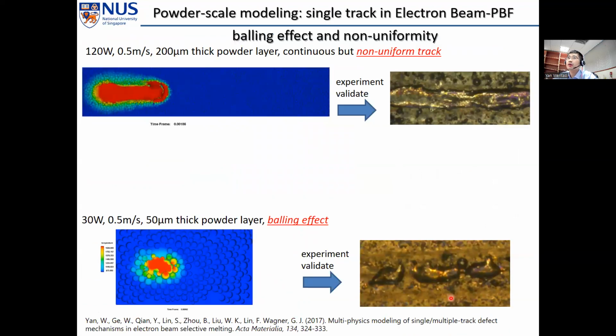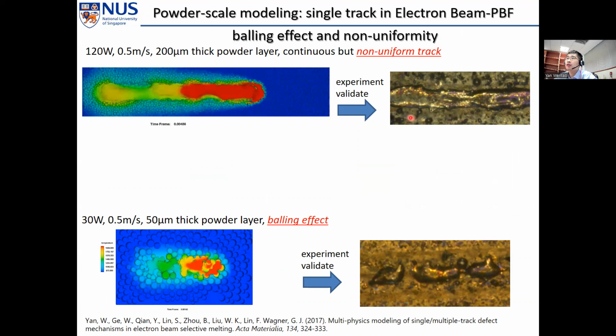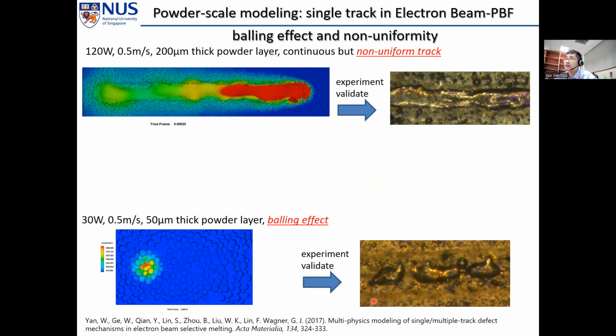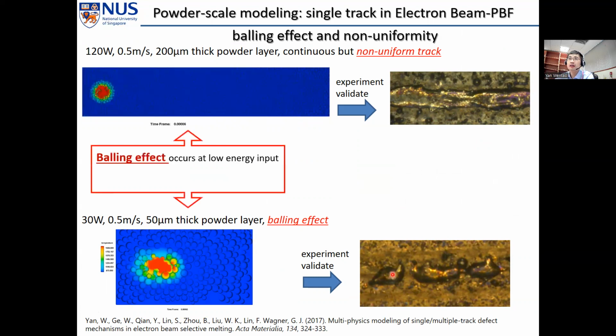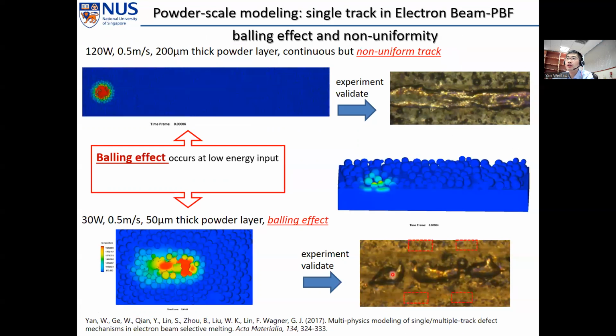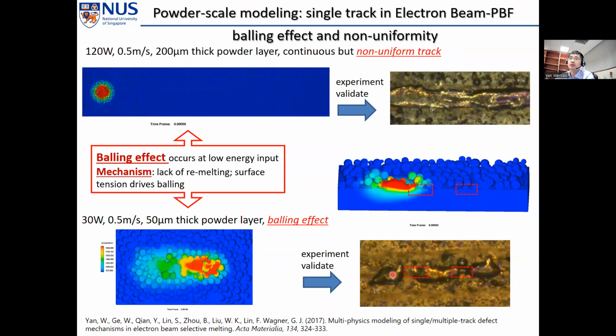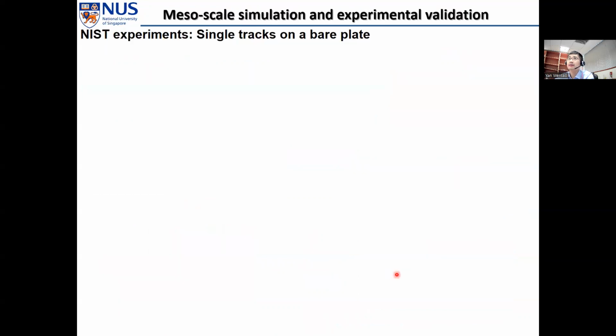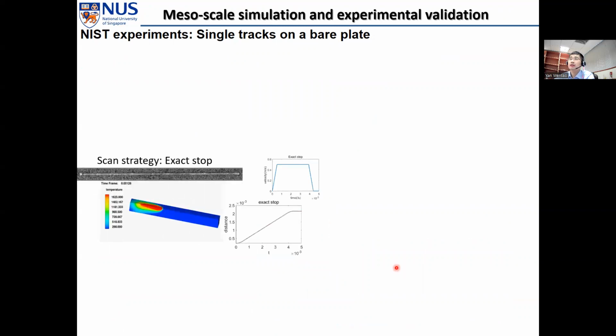With that, we can simulate the very common phenomena like how non-uniform tracks or balling effects happen. And we can reveal the fundamental physical mechanisms, which is actually mainly driven by the surface tension. But essentially, it's influenced or determined by the energy density. And we also do quantitative validation in collaboration with the US National Institute of Standards and Technology.